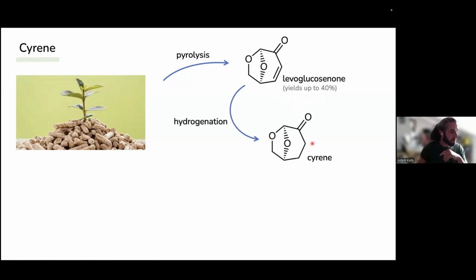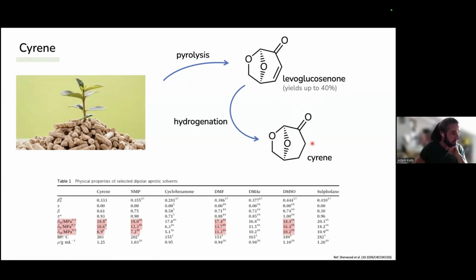Now, the reason we would want to do this is not only because it is a sustainable solvent, but also because the solubility parameters, so the surface energy, for example, these are very similar to solvents like NMP, DMF, and DMSO. And these solvents here, if you go back 10 years when all the processing of 2D materials in liquid phase was begun, then they were using NMP and DMF and all these toxic solvents simply because these solubility parameters were so well matched to 2D materials like graphene and MoS2.